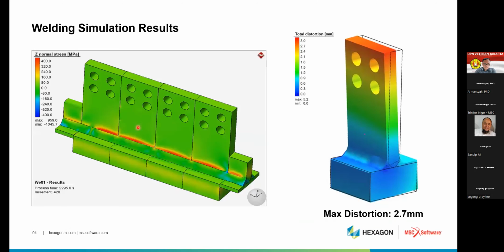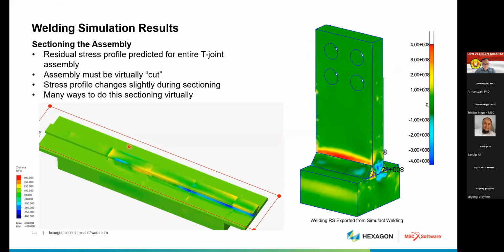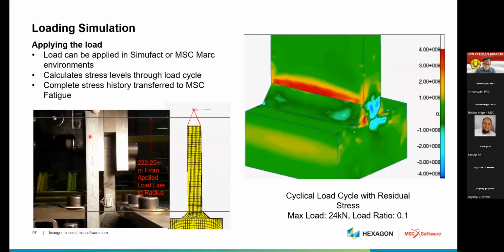And these are the test results, and we can see that the red area means that the highest stress zone is near the weld, and the component might fail at this particular zone. Okay, and this is the distortion, so it is bending towards the left hand side. The black lines you are seeing are the initial position of the component, and the colored one is the final output position. Okay, and this is a cut section of that one, so it showcases that very high stresses are there. And then we take it to the loading simulation.